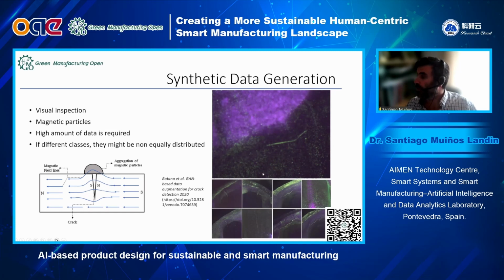And it happens from time to time that you don't have enough data to properly train a neural network to detect them. But using these generative adversarial networks, we managed to generate some synthetic pictures like those that you can see here. Those are real cracks, and those are synthetically generated cracks that we use to train our detection model and improve the performance of the quality control system. So we thought, okay, these generative models work quite well in order to create images, and maybe this technology could be used to also create designs of products. And we had a nice environment to start working with that.